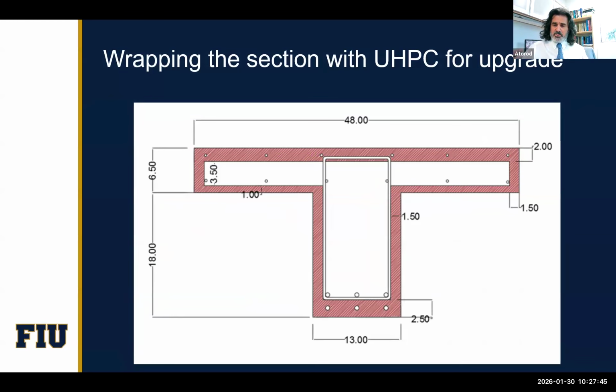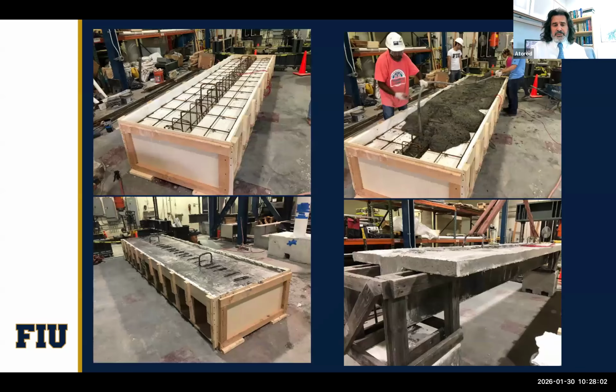girder. At the time, several years ago, we wanted to show that the cheaper way to fix the Venetian Causeway bridges is to wrap it from the bottom. We can spray it with the UHPC, and from the top we can cast in place, and that adds quite a bit. So we did an experiment. We took a T-beam, you can see the T-beam over here, and then we put some additional reinforcement.